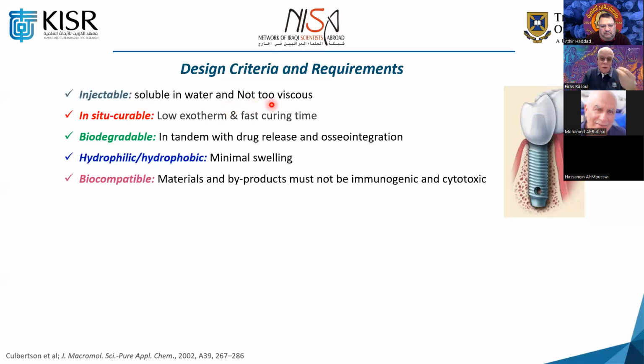It is not very viscous and it is not very soft like water. They need something which has a texture. When it's injected, it can stay in place until you cure it. Of course, you want to cure it. The curing usually, as I mentioned earlier, if the monomer is very thin, like methyl methacrylate and others, tends to produce a high exotherm temperature. And this exotherm temperature might kill the tissues around the implant or the tooth itself. It's called necrosis. So this is one of the issues.